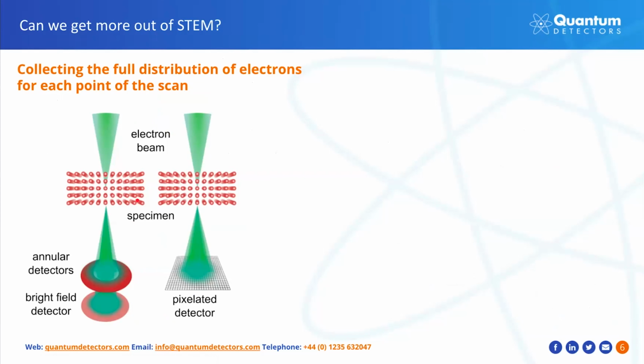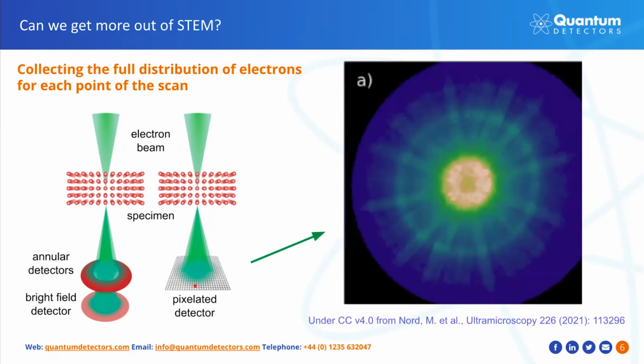The question is, so can we get more out of STEM experiments, and what can we potentially achieve? To demonstrate this, let's collect the full distribution of electrons once it transmits through the specimen. To do this, we will need to replace the set of annular and bright field detectors with a single pixelated detector. The image on the right, which should now appear, is extracted from Dr. Magnus Nord's paper, and shows the beautiful details that are present once we collect a 2D image of the probe for a single position of a scan. So we would be collecting our annular data and bright field data from this. However, we can see there is a lot more contrast. And so, for example, these sets of rings called Laue zones could be used to find information about the third dimension of the sample.